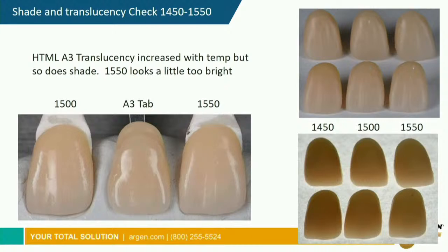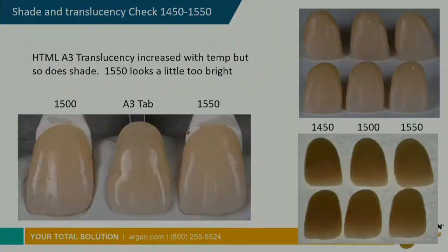Okay? And here, if we just extend it a little further, 1450, 1500, 1550, you see that 1550 looks like it's overdone, it's starting to get bleached out, and 1450 isn't fully developed yet. So the sintering temperature on the multi-layer in particular, and in general, does matter. So we have to be just a little more cognizant of that when we do our sintering.